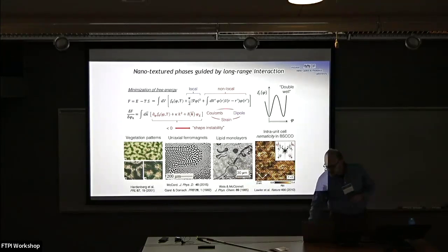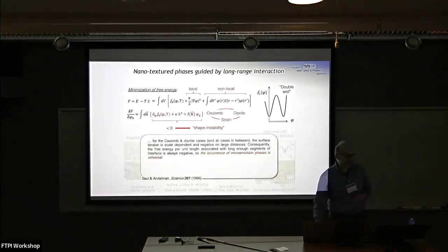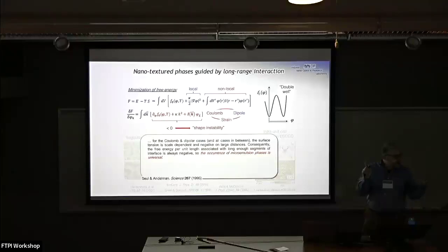And I have the delight of preaching to the choir here with a couple of quotations. One being this one from Seul and Andelman from some decades ago. For Coulomb and dipolar cases, in all cases between this surface tension business, this k-dependent piece of my free energy can be scale dependent. More intriguingly, it can be negative on sufficiently large distances and in particular directions. And as a consequence, free energy per unit length with segments of domain boundaries, let's say, can be negative. So the occurrence of a microemulsion phase is universal.